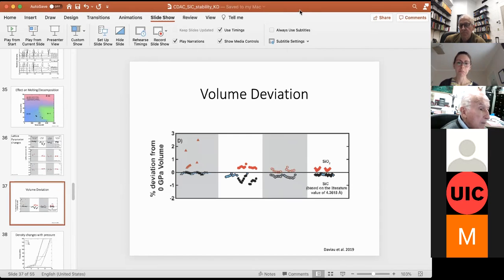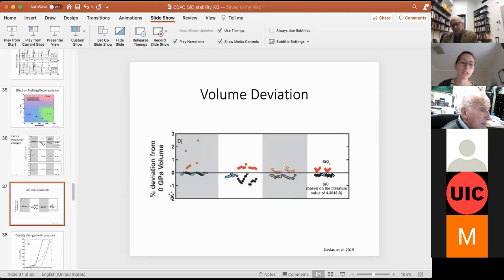But in terms of looking at the amount of carbon in stishovite, we didn't do a calculation to see just how much it was, right? So our volume deviation is pretty small, right? If this is zero and these are the percent deviation from that zero pressure volume, it's not huge, though it does vary. So we are probably at, or at least I think because we also see carbon diamond, we're at kind of a saturation point. So I don't know.